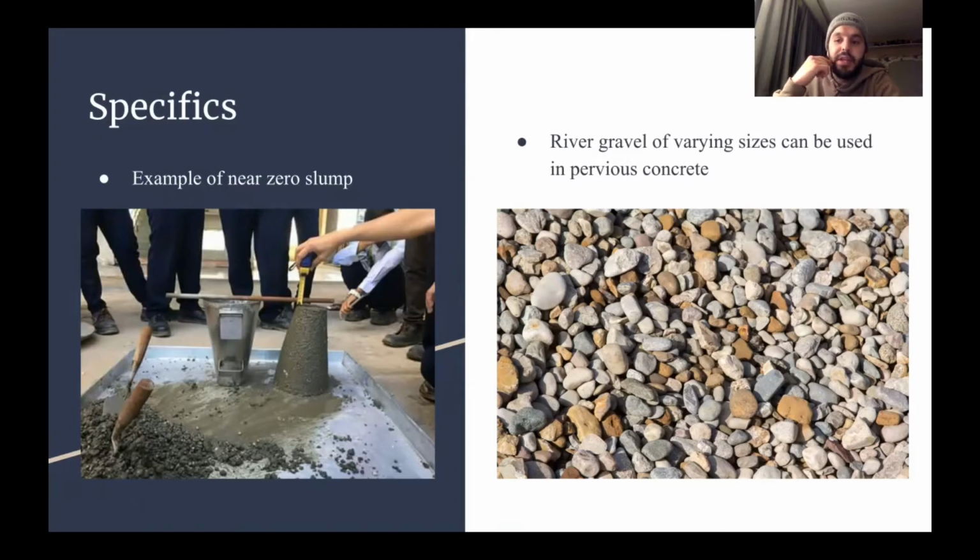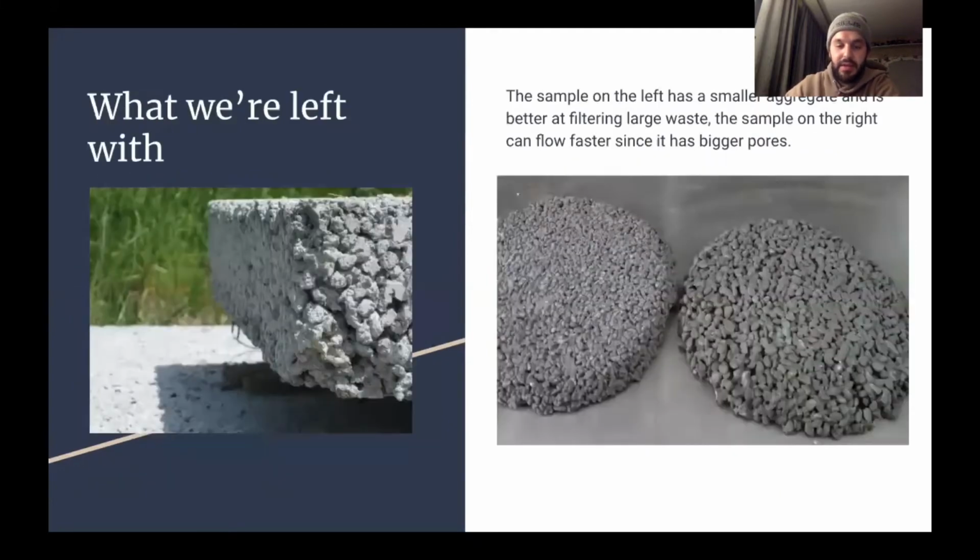They realized that only having mostly coarse aggregates can lead to higher pore sizes and would allow more water to permeate through the concrete and into the ground. This reduces runoff in developed areas and makes projects more sustainable. With a connected pore size ranging from 0.08 to 0.32 inches, they can vary in appearance and specific advantages. It is mostly due to the size of the coarse aggregate.